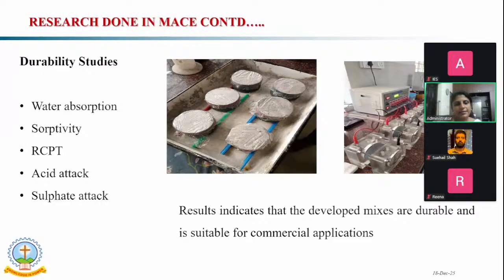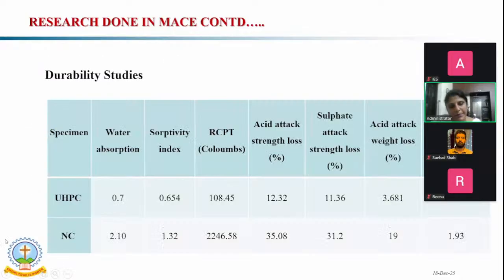These are the results comparing normal concrete and UHPC. In the case of durability studies, the water absorption is too low when we compare with normal concrete. It is only 0.7. Sorptivity index is 0.65. RCPT is 108 coulombs only, but in the case of normal concrete, it is 2200.